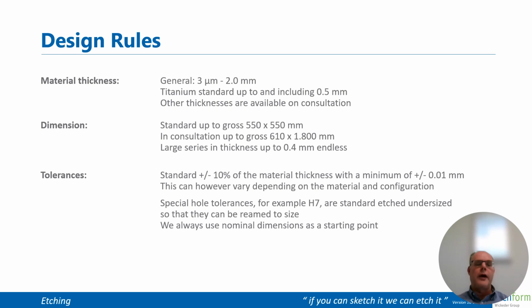There are some design rules you have to take into account. The material thickness: in general, you could say we can etch from 3 microns up to 1.5 to 2 millimeters. In principle, we could etch even thicker. However, there the etching time gets so long that other techniques will be preferred. Titanium is a little bit harder to etch, and there as standard we go up to 0.5 millimeter. However, we have also done some etching onto thicker materials, so that's on consultation.